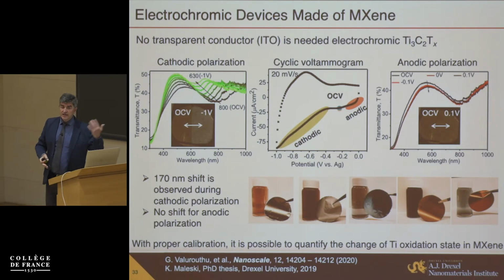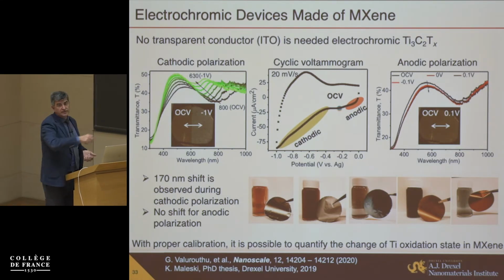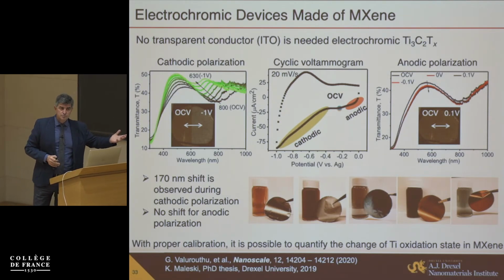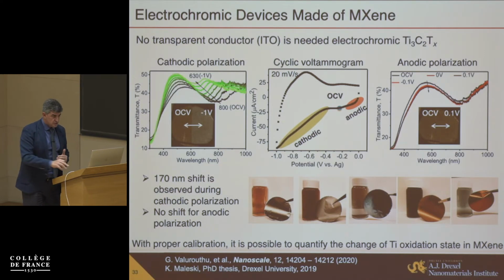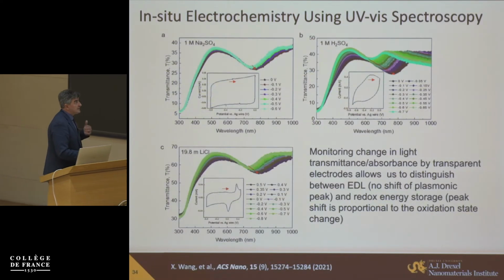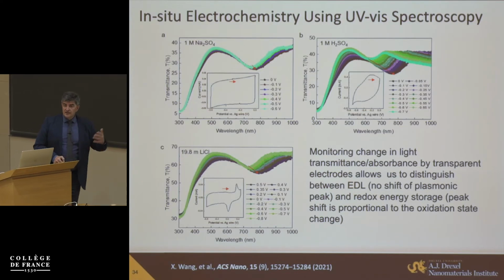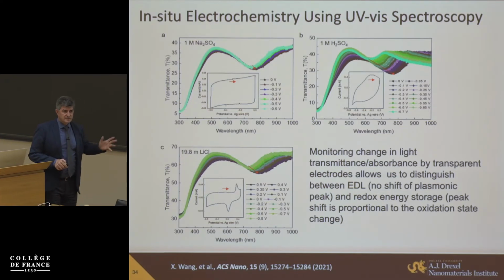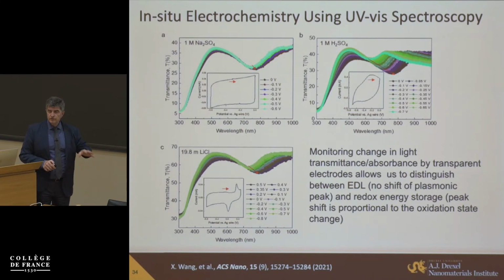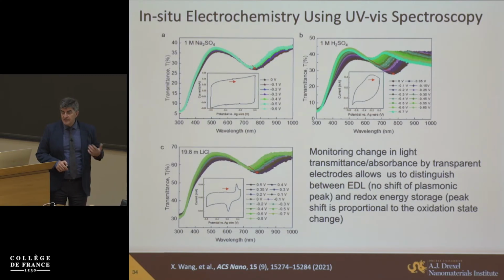And you can record it, and you can calibrate the shift against the data I showed you from X-ray absorption spectroscopy, and know, for example, how much the oxidation changes here. And we developed a technique, which we have applied by now to at least 6-7 different MXenes, several oxides and conducting polymers, that allows us to distinguish between behaviors. For double layer, you have polarization and a small shift, and if you plot it as a function of potential, you basically get a straight line with a certain small slope.